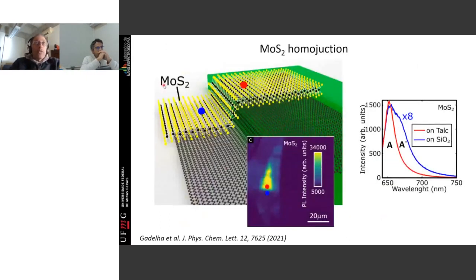And if I go now to the MOS2 and I do something similar, I also have a junction here, okay, the small doping, half doping. But now I will look into the luminescence, and I see that, again, if I look into the blue or the red area, I have different luminescence spectrum. And the MOS2 has the formation of excitons.